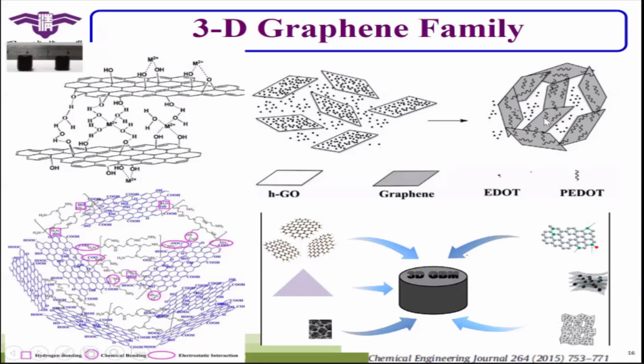What we want from the three-dimensional structure, on the right-hand side here, you will always see that they have a two-dimensional frame. So they can keep the electrochemical property of reduced graphene oxide or the graphene family. But they have a lot of space inside. This space can hold some electrolyte. With the electrolyte, their electrochemical property will be enhanced, especially when they serve as electrode materials for lithium-ion batteries or supercapacitors. So for the three-dimensional graphene family, a lot of people would like to use them as very novel electrode materials for energy storage and energy conversion. That is the case here.